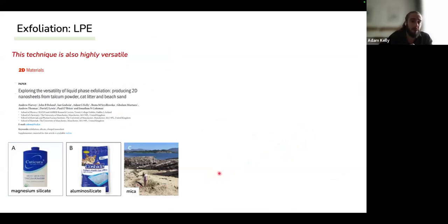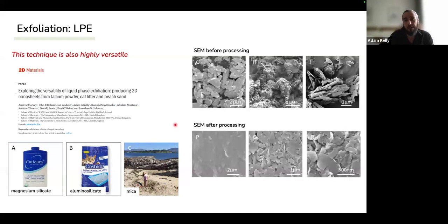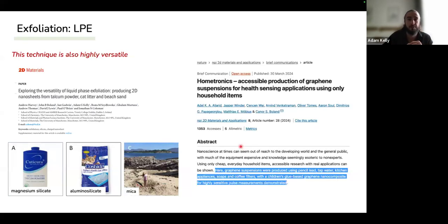We published a paper here where we got talcum powder from a supermarket. We got cat litter also from a supermarket, which is an aluminosilicate. And the PI that I worked for, he had his kids dig up some sand at a beach, and we brought this into the lab. We applied this liquid phase processing technique. This is the SEM of the material as we picked it up, and we applied these techniques, and we got nanosheets out at the end. So it doesn't really matter where the material comes from, what it's composed of. As long as it's a layered crystal, we can apply this process to it.